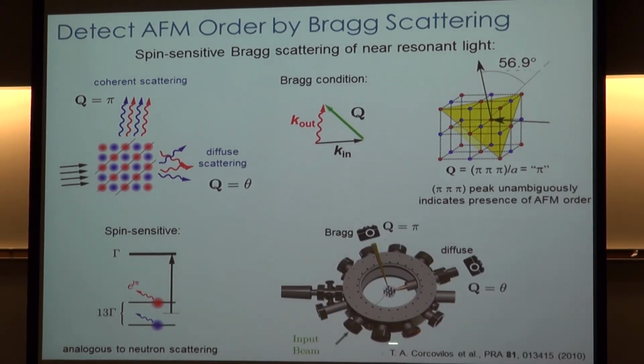So here's what the actual apparatus looks like. This is without its lid, magnetic field is coming out of this cylinder. And we have an input beam that is at this particular angle to the symmetry planes of this three-dimensional square lattice. This is the pi direction. That corresponds to this direction. And this is some other direction. The other direction is just for normalization. It's another way of making sure that what we're seeing is really due to that particular Bragg angle and not something else. So this is what we call the diffuse scattered light. It's here. In every direction, there's some spontaneous emission. We call that the theta direction.